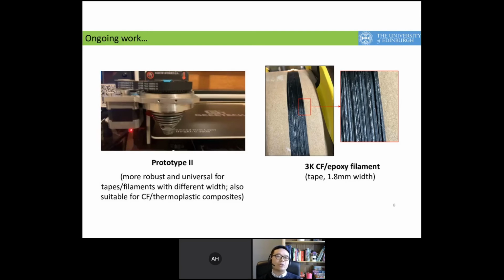To take this technology further, we also developed a second prototype, which is more robust and universal for different types of filaments at different sizes. It is also suitable for printing carbon fiber reinforced thermoplastic composites. On the other hand, we managed to produce some slightly larger filament using 3K fiber tows. The new prototype will allow switching between different filaments, so we can achieve a good balance between high print quality and fast deposition rate. There will be more work coming out very soon.